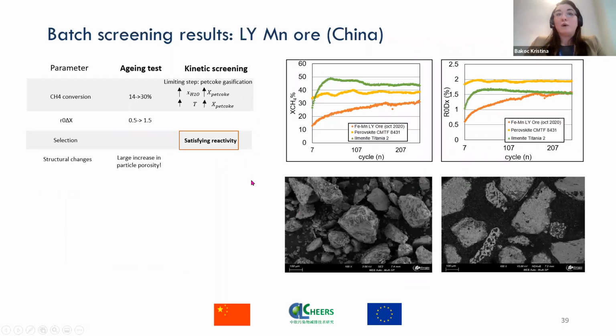Following with the results of LYMN ores from China, we see similar trends of activation as we have seen previously with ilmenite. However, the values for methane conversion are somewhat lower. Still, overall reactivity of the material is quite satisfying, with one important addition: during the characterization of the material after the activation tests, we have noticed a certain increase in particle porosity, which could indicate higher affinity for attrition. And this is important for particle lifetime overall.